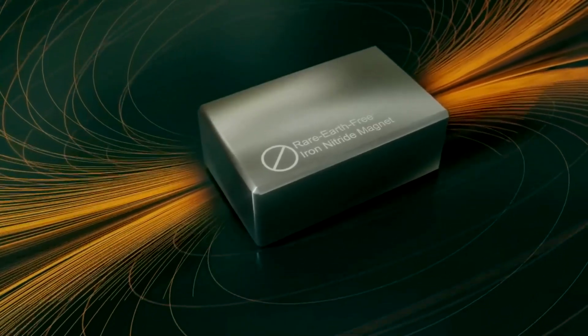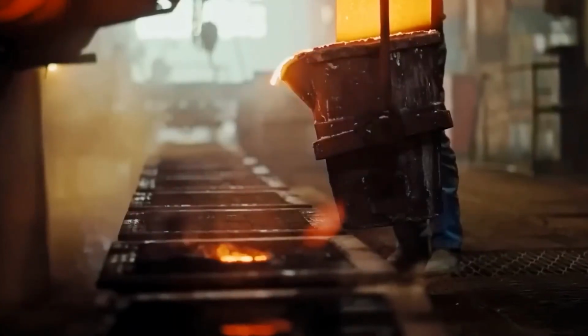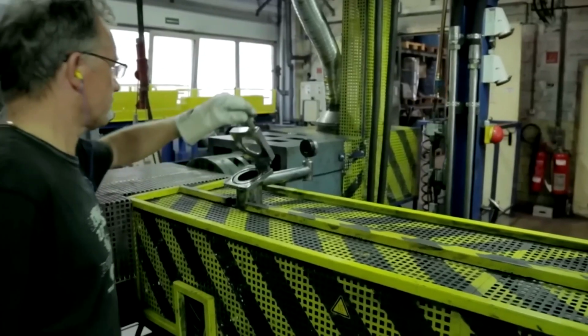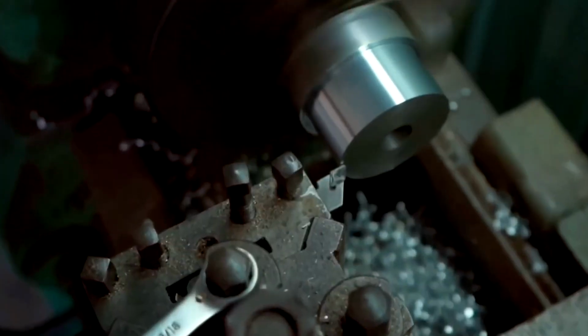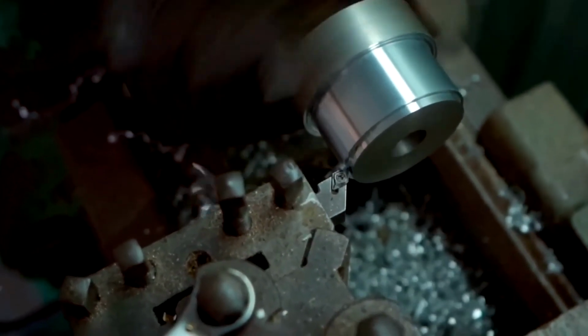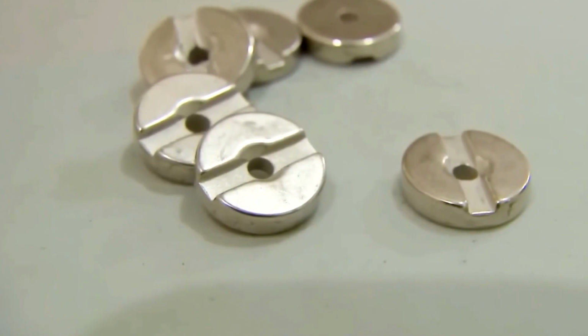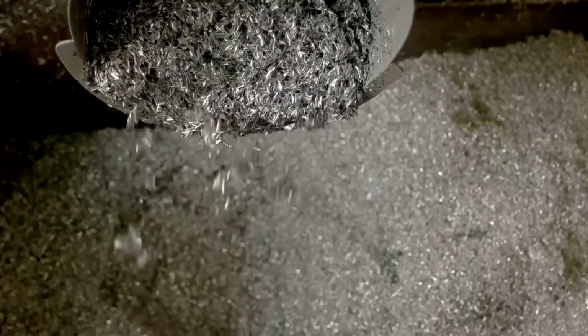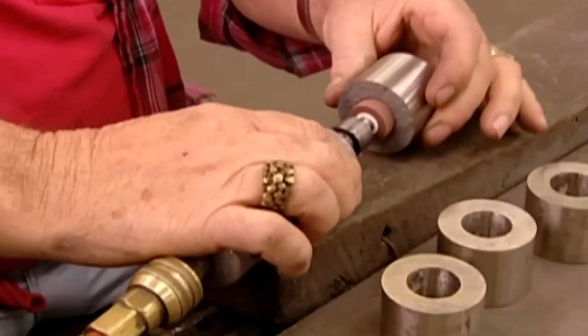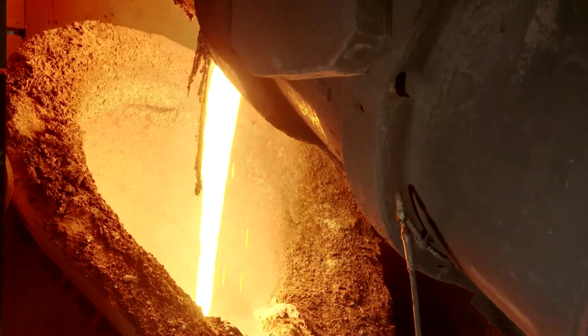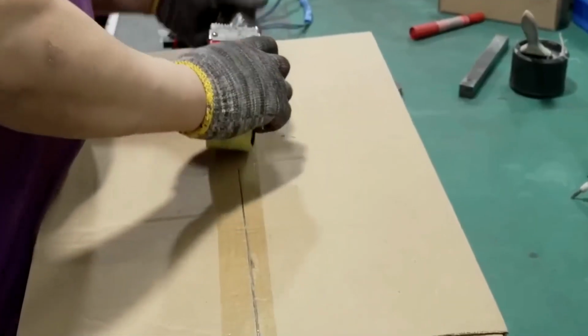If the pulse is too strong, it can distort the crystal structure. If too weak, some domains will remain disordered, causing a noticeable drop in magnetic strength. After this jolt of energy, each magnet's surface field is measured with a Hall sensor, and its polarity is verified. Those that fail are demagnetized and reprocessed, while the qualified magnets move on.